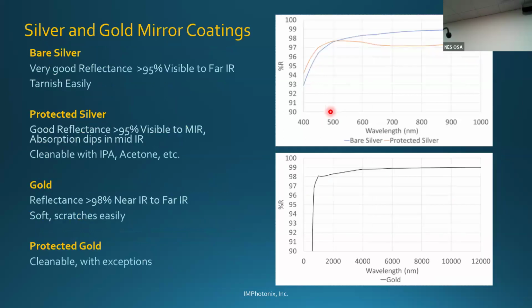And just rounding out the other metal coatings would be silver and gold for reflective purposes. Bare silver has very good reflectance. You're usually getting above 97%, 98.5% in the near infrared, and it has good reflective qualities in the visible, way beyond aluminum. The downside, again, is that silver is a soft metal and it needs to be protected. And we, when I say we, I mean people in the industry, will put a quartz overcoat or a sapphire overcoat onto the silver. You do lose some reflectance. You can see on the top curve, it's expanded out scale, so it will drop to 96.5, 97%. But depending on the thickness of the overcoat, you can tune where you want the peak reflectance to be.